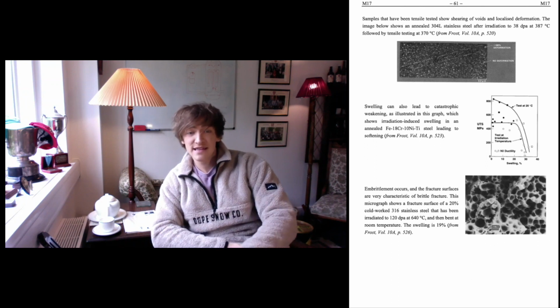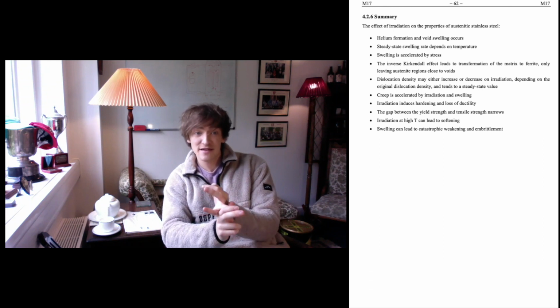And really, that's stainless steels. We've covered a fair amount there. We've covered a number of areas, but the key effects of irradiation are helium formation and void swelling can occur. Steady state swelling rate depends on temperature. Swelling is accelerated by stress. The inverse Kirkendall effect leads to transformation of the matrix to ferrite, only leaving austenite regions close to the voids, so we start to get different corrosion risks. Dislocation density may either increase or decrease on irradiation depending on the original dislocation density, and it always tends to a steady state value.